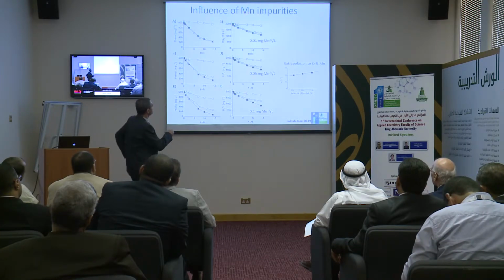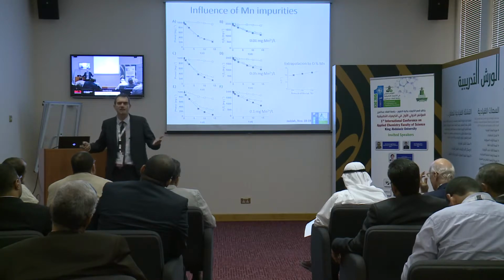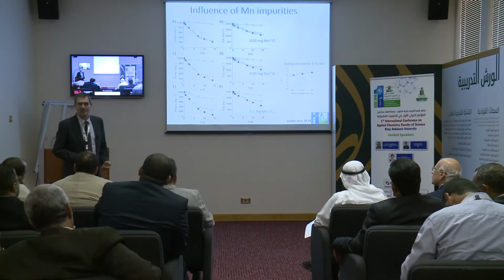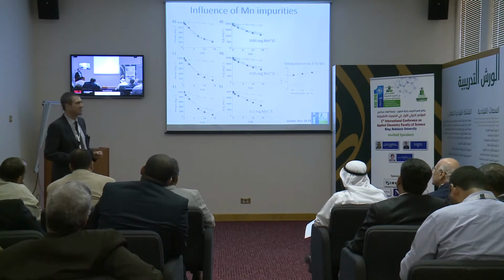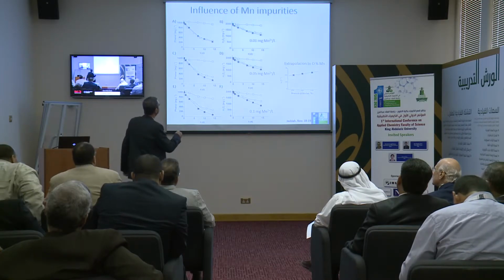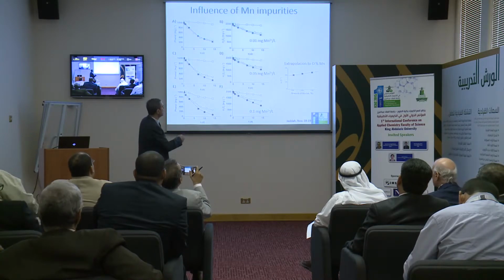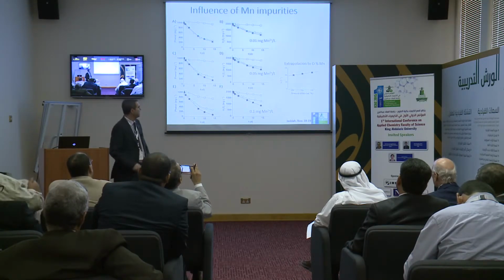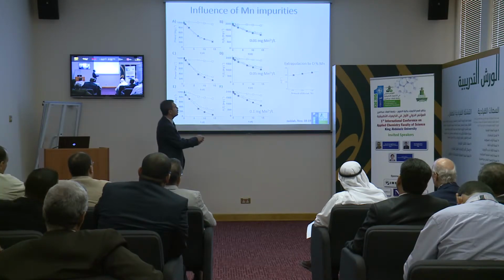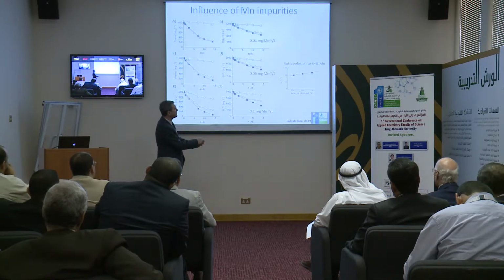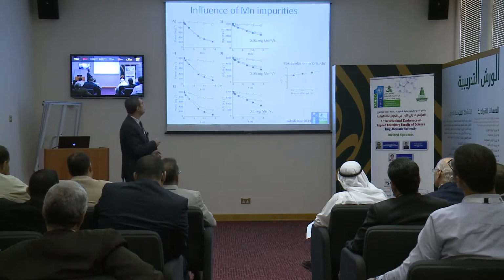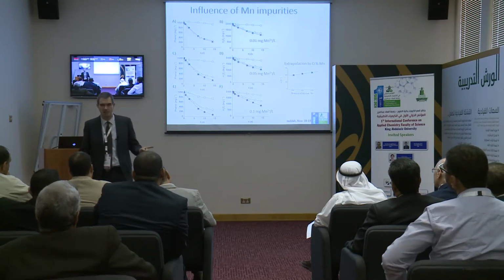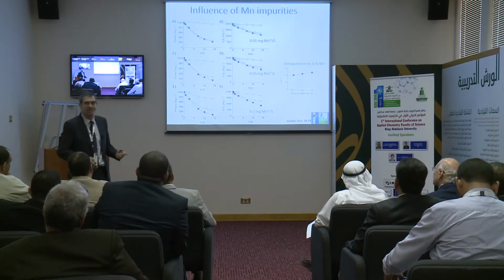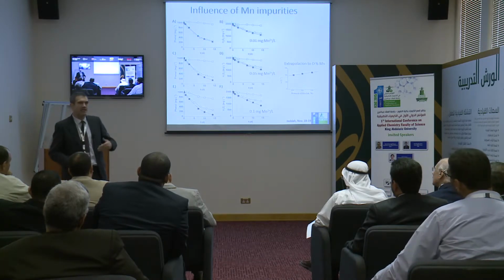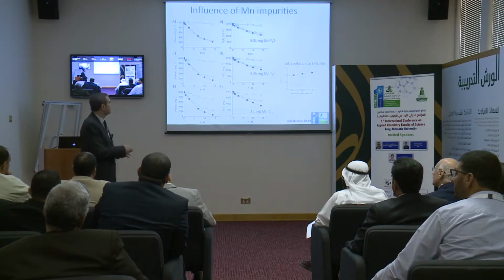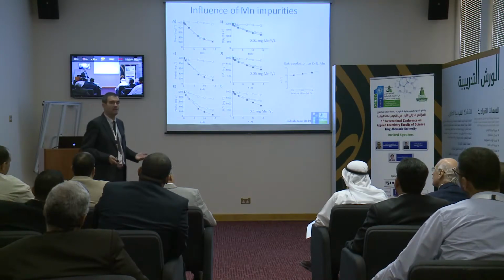One thing that always worries in using graphene as metal-free catalyst is whether there is any impurity, any metal present that is acting as catalyst, and we are confusing the small amount of metal and thinking that it is the carbon. So we on purpose made some experiments in which we add different amounts of manganese to see the influence of the presence of manganese in this amount. And this is just the conclusion of this, in which we plot the reaction rate constant against the amount of manganese that we on purpose add. I have to notice that these samples of graphene have never touched manganese, have never touched any metal. But manganese is one of the typical metals that promote the Fenton. And maybe during its life, the insect or the shrimp has been in contact with some metal, so maybe chitosan contains some metal, or maybe the algae contains some metal.